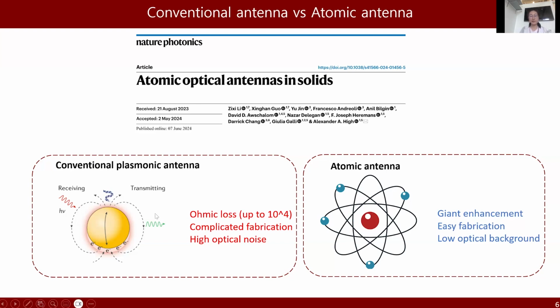So the near-field enhancement from a plasmonic antenna is typically limited to 4 orders of magnitude. Besides that, to fabricate such a plasmonic antenna, we need very precise control over the shape and the size of the nanoparticle, and this causes some difficulties in nanofabrication. Additionally, the laser power required to activate such a plasmonic antenna is usually on the level of tens of microwatts to hundreds of microwatts, and this will induce a lot of optical background noise.